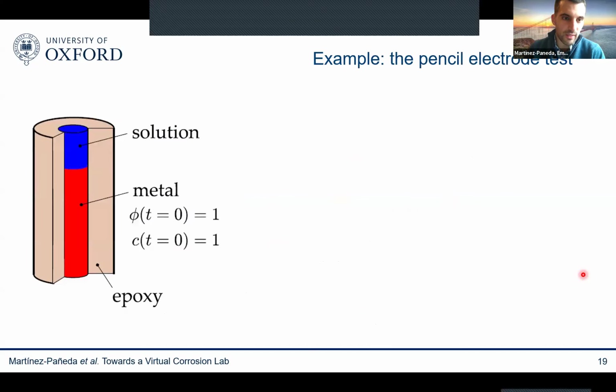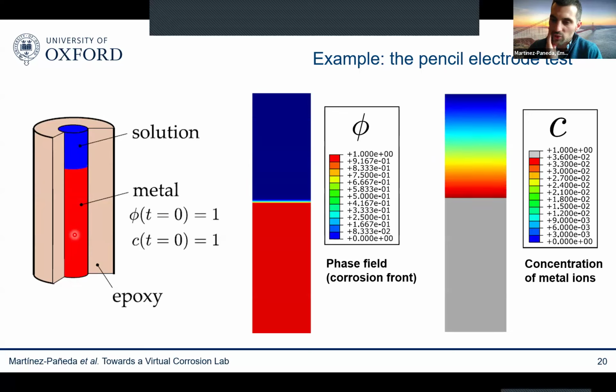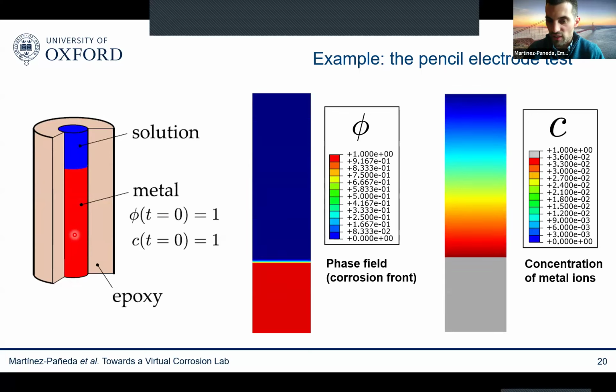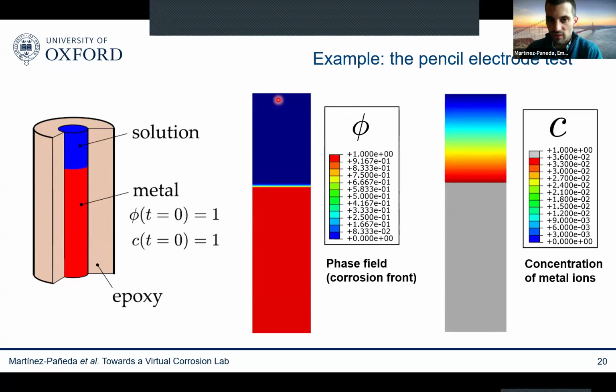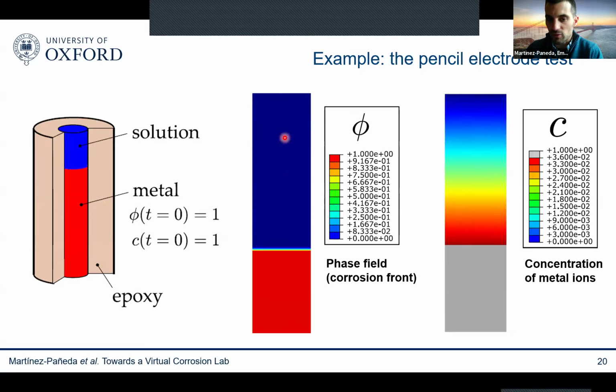Let me show you how this works. I'm going to start with a very simple example, the simplest I can think of. This is a classic benchmark in the corrosion community. It's called the pencil electrode test, and it's very simple because you effectively have 1D corrosion. You have a metallic bar that is corroding basically in one direction, so it's effectively 1D. And you can see how it works here. So on the left, you are seeing the evolution of the phase field, the evolution of the corrosion front. You can see how the metallic bar is corroding.